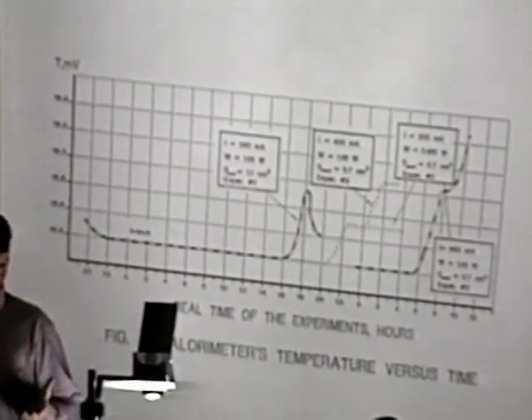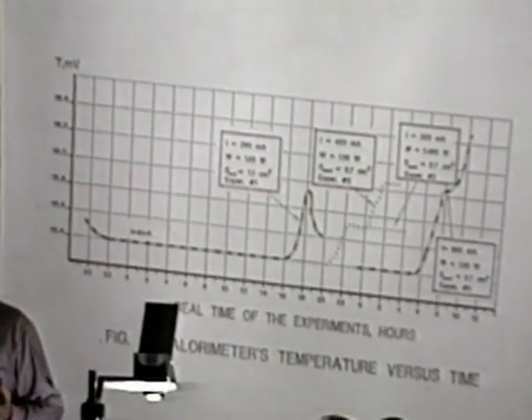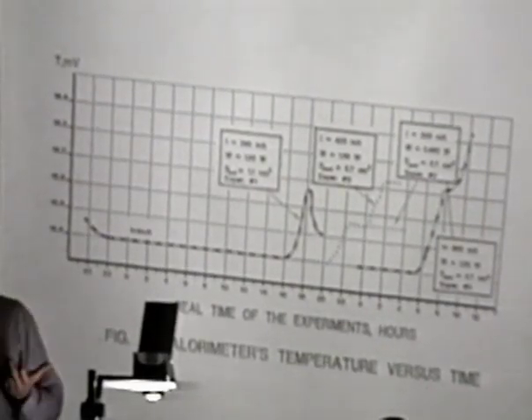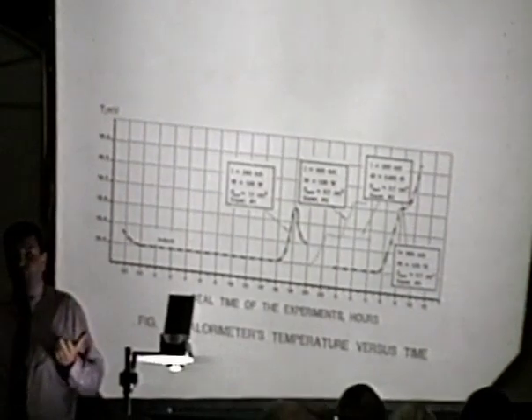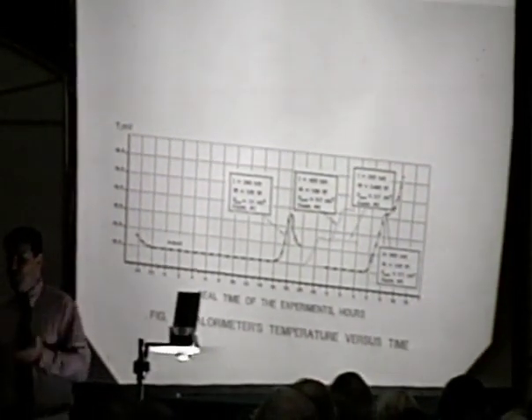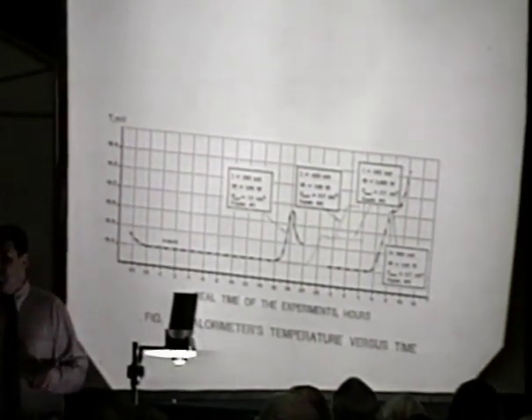It made us really curious. But anyway, we did this. So we used pure beryllium oxide cast, and we melted pure palladium tubing to make the anode. However, we cannot guarantee that this is still pure because we used just a regular torch.